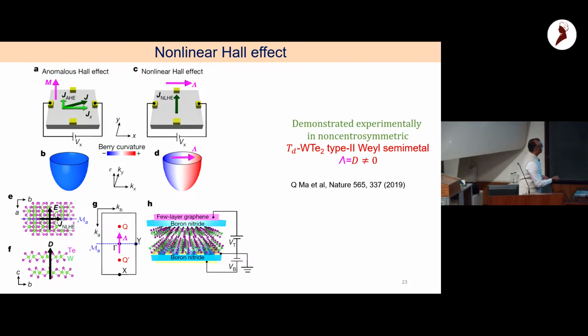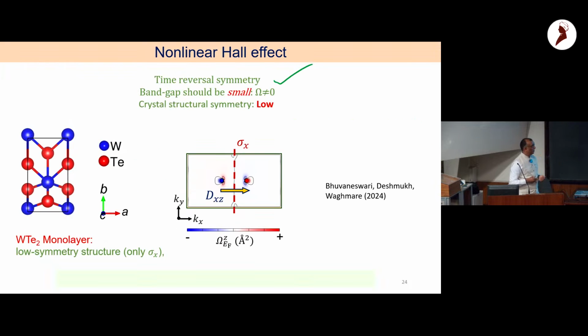And what is interesting is the linear Hall effect always has a current which flows at an angle, because at a frequency omega, you have a current in the x direction as well as a Hall current with the same frequency. So it's at an angle. But in the nonlinear Hall effect, the beauty is the signal is exactly perpendicular because there is no second order effect along that longitudinal direction. So that's the advantage of the nonlinear effect, although it's a weaker effect. So you get this beautiful nonlinear effect, and they demonstrated it nicely in this paper experimentally.